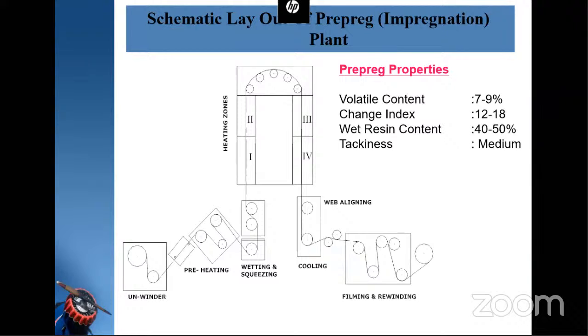So this is another important technique called impregnation of the fiber with the resin system, called impregnation plant or prepreg plant. Here you can see the schematic diagram. Here the fiber comes from the unwinder and gets heated in a preheating chamber where volatiles are evaporated. You can heat up to 80 or 100 degrees centigrade, and then it gets into a squeezing station where the resin is available, and it gets mixed with the resin, and the excess resin is squeezed out between the two rollers. Then it passes through heating zones 1, 2, 3, 4, where each zone is maintained at a different temperature so that all the volatiles are evaporated, and it gets cooled in a cooling roller chamber, and then it gets wound onto a roller.